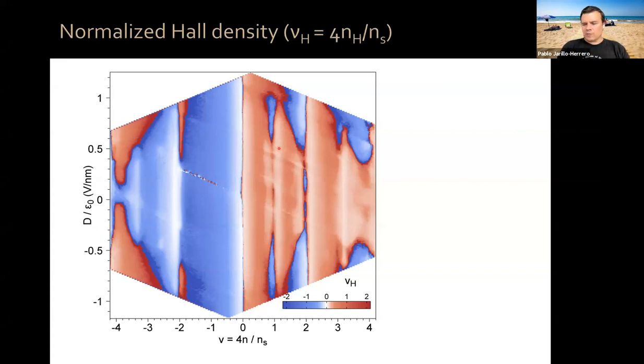So first, some features correspond to a gradual change in sign of the normalized Hall density, okay? Normalized Hall density goes from negative through zero smoothly to positive. That's a behavior that corresponds to gap or Dirac points, okay? Why? Because when you reach a gap or a Dirac point, your density of free carriers is zero, so your Hall density goes through zero smoothly, okay? That happens here, for example, at charge neutrality. You see you go from dark blue to light blue, white, light red, darker red, okay? So it happens at charge neutrality.